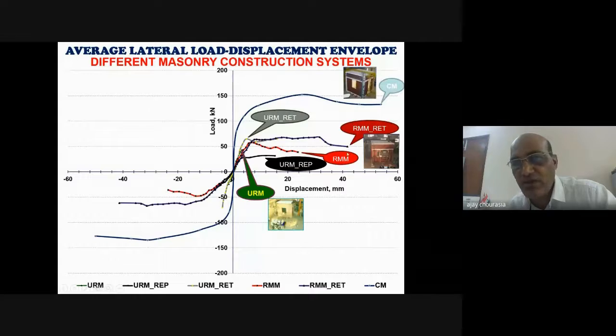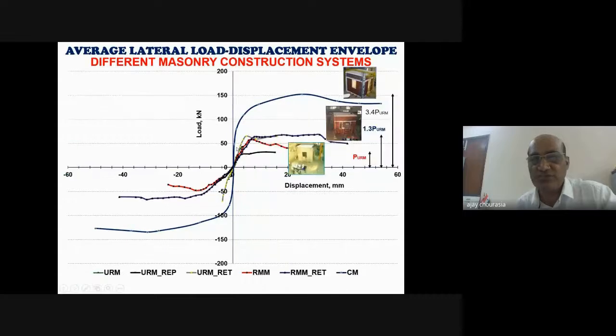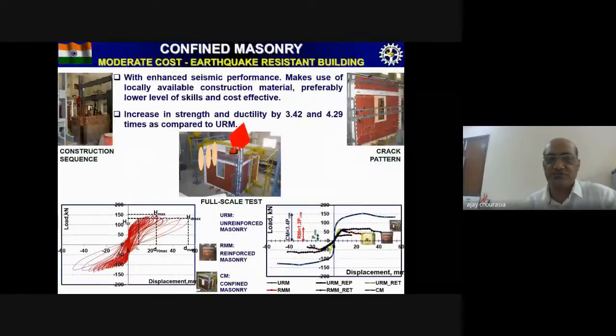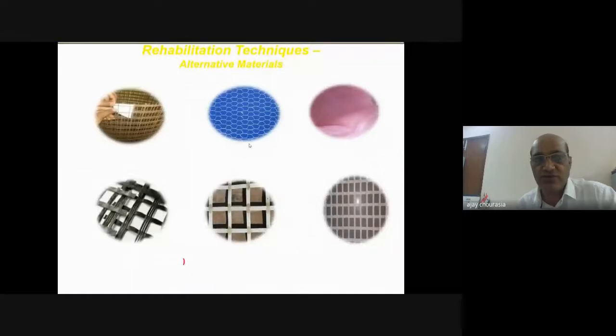Deformability capacity for URM, RMM, and confined masonry has gone from 11 mm in unreinforced masonry, to 22 and 24 mm in the case of RMM, and around 54 mm in the case of confined masonry. So the strength also increased. In short, confined masonry promises a robust seismic performance in terms of strength, stiffness, ductility, deformability, and energy dissipation capacity when compared with unreinforced masonry and reinforced masonry. This is what I have already discussed.